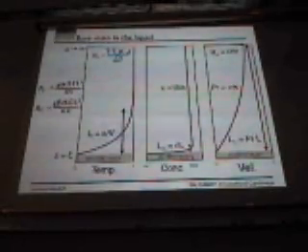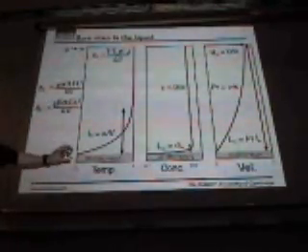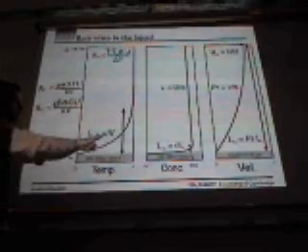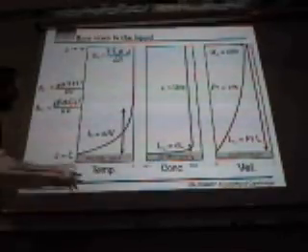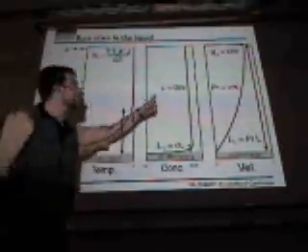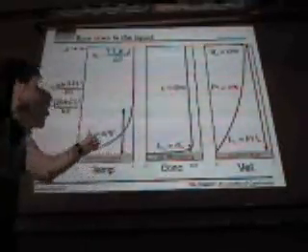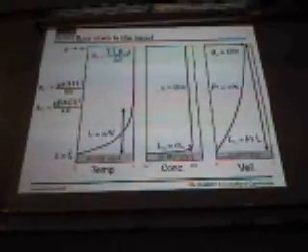So now if I take that sort of steady state system and I look at steady state properties in front of this mushy layer, what do they look like in the liquid? Well, there are three length scales that really govern this system. One is a thermal length scale, which is simply the thermal diffusivity divided by the growth velocity. There's a much smaller length scale, which is the diffusivity of the solute divided by the thermal diffusivity times the thermal length scale. So that's really the length scale over which composition diffuses.